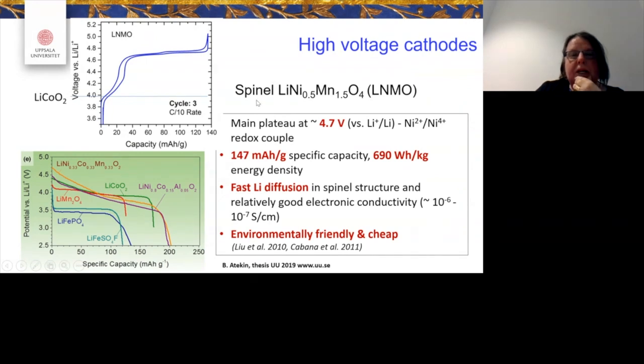It's a spinel structure, it's cubic, so the lithium ions can go out and in the three dimensions in this compound. And it's what's called a high voltage cathode. And that is then giving you the high capacity. And I put in the lithium cobalt oxide here, which is typically one you have in your mobile phone. So you can see that this plateau here is for lithium cobalt. So it's really giving a lot more of the capacity.